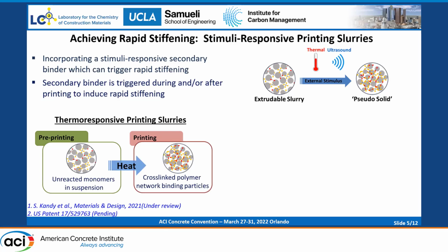We develop thermoresponsive suspensions by incorporating thermosetting resins in the suspension and using heat as the trigger to trigger the rapid stiffening. So when we heat it, these monomers undergo polymerization and induce a gelation in the suspension that induces a fluid to solid transition in the suspension. So we can heat these suspensions in a single stage, either in the nozzle, or in multi-stage in the extruder as well as the heater, or we can heat this immediately after printing, after depositing the layer.